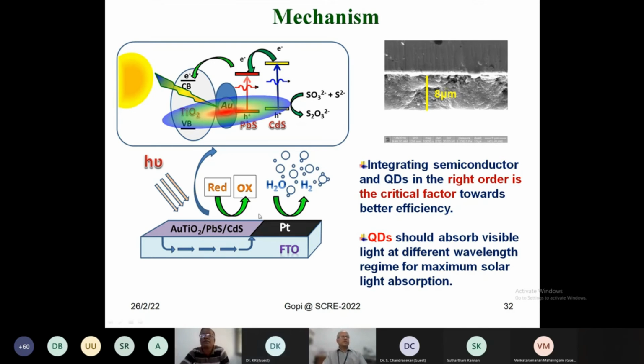Please go ahead, sir. Okay, so this is just to explain the mechanism of the photocatalysis, what we reported actually. Here you can see the band arrangement of cadmium sulfide, lead sulfide, and titanium, and then gold acts through surface plasmon resonance, through field effect it happens. The electron transfer also happens from cadmium sulfide to lead sulfide to titanium. So that means electron flow will be in only one direction. That way we are able to simulate nature actually.